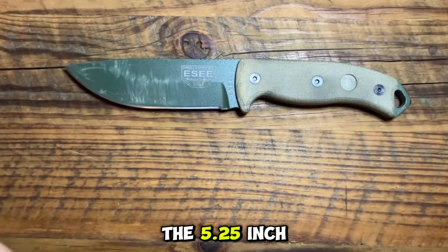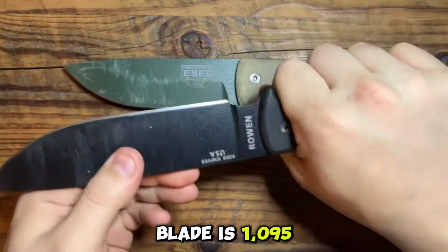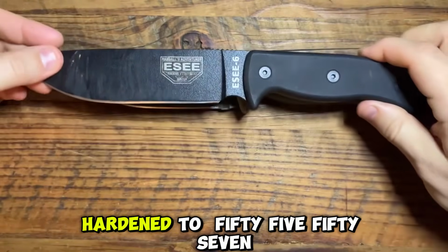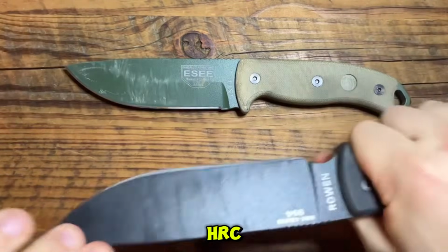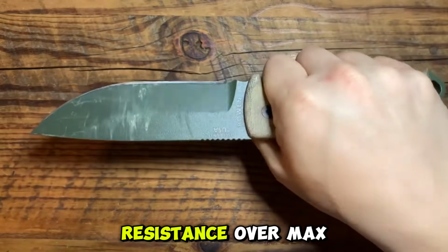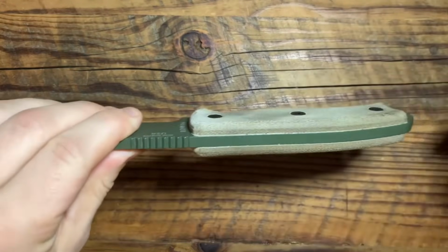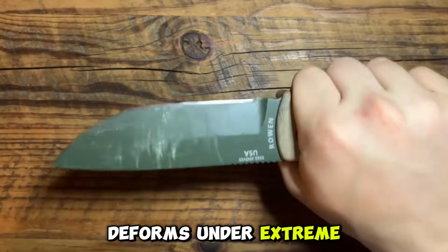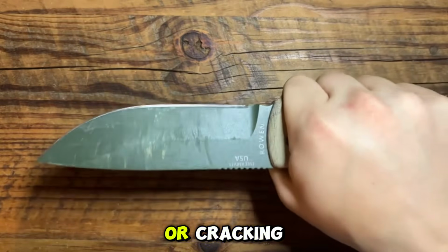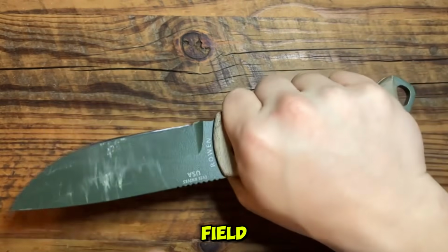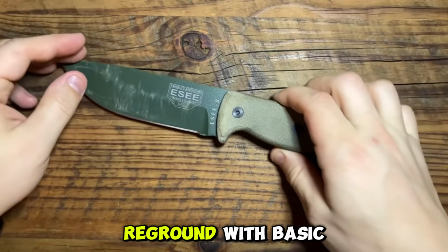The 5.25-inch blade is 1095 high-carbon steel hardened to 55-57 HRC with a toughness-first heat treatment that prioritizes impact resistance over max hardness, meaning the edge deforms under extreme stress instead of chipping or cracking, which matters a lot in the field since a deformed edge can be reground with basic tools while a chipped one can't.